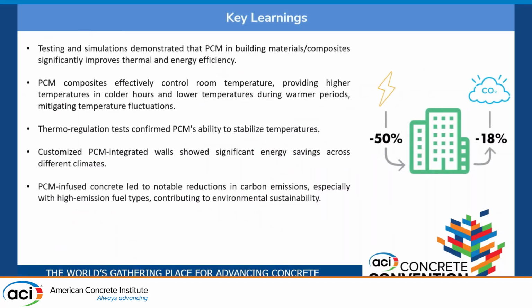So, some key learnings: we have achieved a really good thermoregulatory test result. We have simulated this, and we did some energy analysis. What we found out is that we can effectively control the room temperature. We can provide higher, warmer room temperatures during the nighttime. We can provide lower, colder room temperatures during the daytime at the peak temperature hours. And we can definitely achieve notable reductions in carbon emissions by using phase change materials.